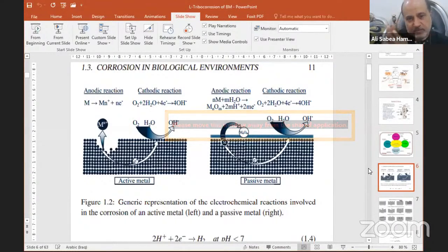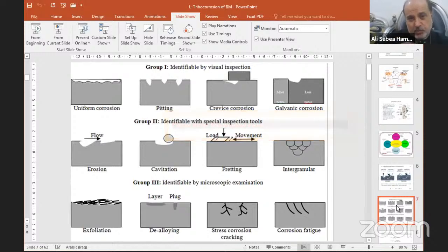Corrosion in biological environment can be seen as an anodic reaction and a cathodic reaction in active metal and passive metal. The materials that can be used in biological environment, in medical application, may be cobalt chrome alloy, titanium alloys, or stainless steel. Active-passive behavior can occur for these metallic materials, with this anodic reaction and this cathodic reaction. In corrosion, by visual inspection, can be seen uniform corrosion, pitting, crevice corrosion, and galvanic corrosion.